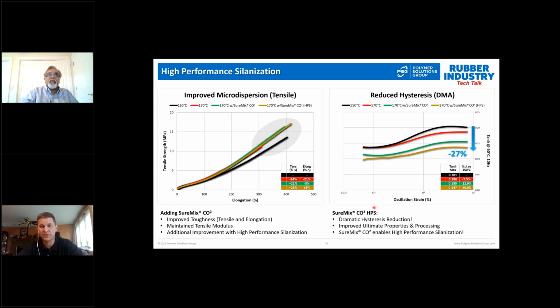The problem is in that red curve, you just can't mix it. It just can't be done. Processing is way too difficult. Using SureMix CO squared, we've shown that we're able to process it, and we're able to maintain the tensile strength. But here you see the dramatic reduction in the hysteresis.